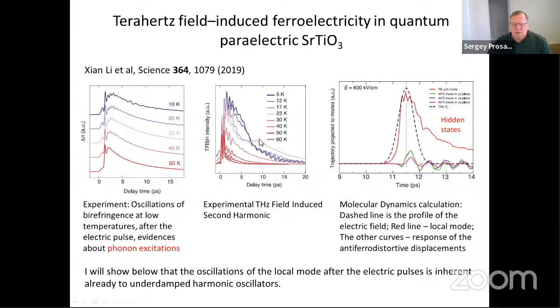The second slide shows the second harmonic after the electric pulse, and we see that at low temperatures, so 5 Kelvin is the blue curve, which is the widest. So the lower the temperature, the wider the response of the second harmonic. And also we see oscillations of the second harmonic, which are probably due to phonon excitations, like in the first slide. As temperature increases, the response gets thinner and thinner, and finally at 60 K, we already do not see strong oscillations after the pulse, and the response is rather thin.